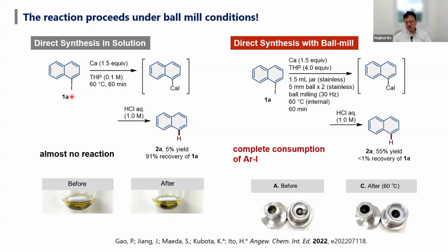But under ball milling reaction conditions, calcium can react with organic halide very quickly to form organocalcium reagents. This is a picture before ball milling, and this is a picture just after the ball milling.